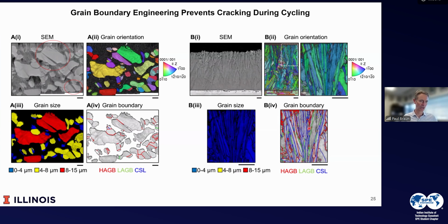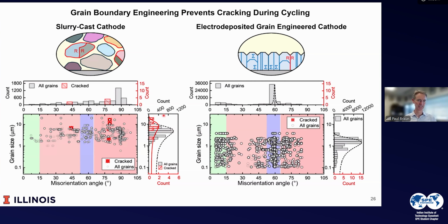And so we did a larger statistical analysis of cracking and misorientation angle. And what we see is that cracking occurs only in these high angle grain boundaries. That's the pink regions here. On the other hand, when we electrodeposit, you see that there's virtually no high angle grain boundaries, and the grain boundaries are clustered between being the low angle grain boundaries and coincidence site lattice boundaries. And so these are quite stable. And these boundaries here in between are not present the way they are in the slurry cast system. And the net effect is a dramatic reduction in cracking.